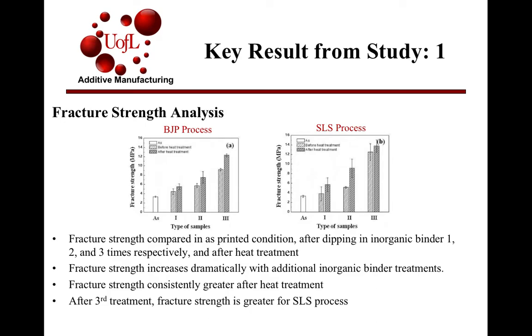The first key result of this study is the fracture strength. As you can see, the chart on the left is for the BJP process, and the chart on the right is for the SLS process. The authors compared the fracture strength for both processes, for pre and post heat treatment, and for treatment with the inorganic binder 1 time, 2 times, and 3 times. All of those conditions are shown on both of these charts.